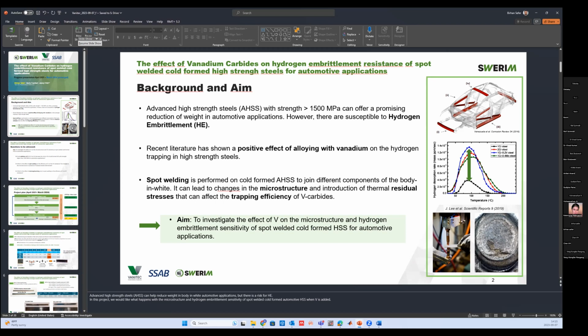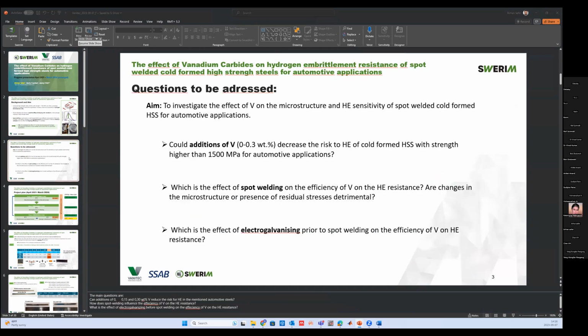So in general, the aim of this project is to investigate the effect of vanadium on the microstructure and hydrogen embrittlement sensitivity of spot welded cold formed high strength steels used in automotive applications. There are three questions that we would like to address in this project. The first is whether additions of vanadium in the range of 0 to 0.3 weight percent can really influence the risk of hydrogen embrittlement of these steels with strength over 1500.